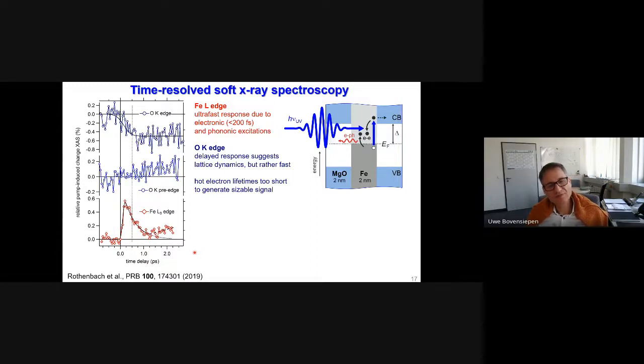But now, how can we discuss the data? Let's start here with the iron L3 edge. There we see a response within 100 or 200 femtoseconds, where we see the maximum in the pump-induced X-ray absorption change, and then a drop of intensity. So this might remind you about the 2-temperature model that I introduced earlier, where we have first hot electrons and then interaction and cooling of the electrons because of electron-phonon coupling. So here, this could indeed be due to electron-phonon coupling, and this fast response is the excitations of hot electrons and electron-electron scattering.